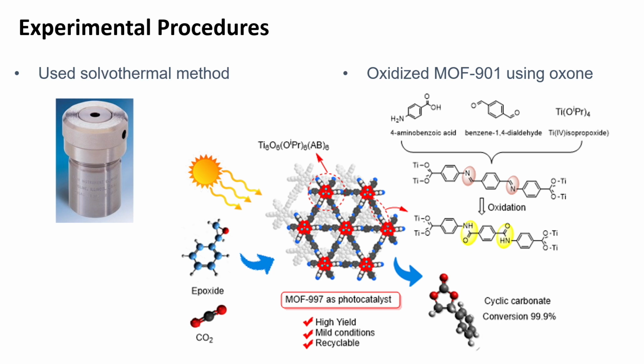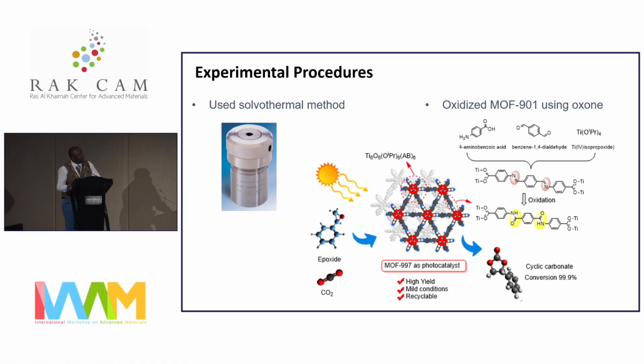Following through, or copying from this work, we decided to apply this methodology to metal organic frameworks by choosing MOF 901, which is a MOF that combines COF and MOF chemistry, through converting the imine linkages in this MOF into amide bonds. We used oxone as the oxidizing agent, and after that, we were able to test the performance of these two materials for cycloaddition of CO2 onto different epoxides.